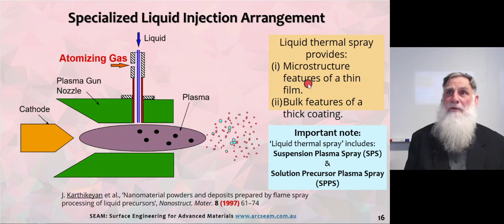So the liquid thermal spray provides microstructural features of a thin film, but, and this is a big but, the bulk features of a thick coating. So we're getting the features of both thick and thin being formed simultaneously. An important note here is that I'm using the term liquid thermal spray. That includes two techniques, one which is called suspension plasma spray, SPS, and the other technique which is called solution precursor plasma spray, SPPS. And again, there is a seminal paper by Karthikeyan et al.